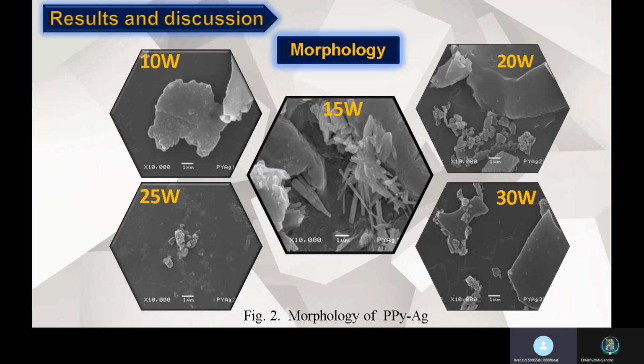The surface was homogeneous and smooth, with a good mix between polypyrrole and silver. The most interesting morphology was at 15 watts. In this photo, you can see rods. This kind of morphology can function as a network to capture electromagnetic waves.